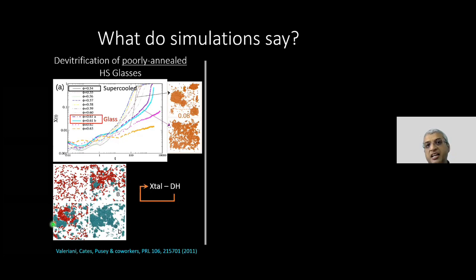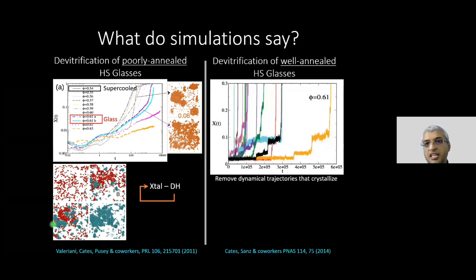Now they also did another bunch of simulations in which they had a whole bunch of ensembles of these glass samples in the simulation box, and every sample that had a tendency to crystallize soon, they removed from the simulation. So they only looked at glasses that crystallized after a very long time, and they called them well annealed glasses.